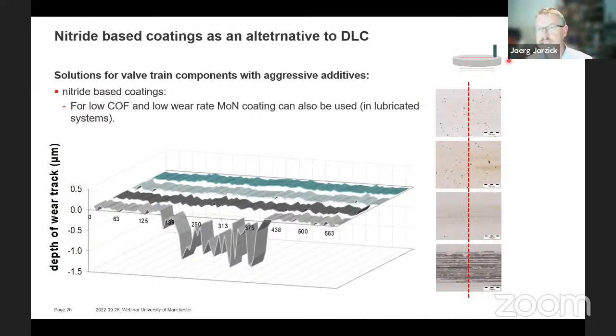So basically we coated a disc, and then we put a pin on this, and then we had this reciprocal wear test, which is a kind of standard test. And we used different types of oils, and we had a look at the wear track, and here's a picture of the wear track, and then we measured the profile across the wear track, which is displayed here. So let's start with the dark gray line. Basically, this is the standard DLC coating with a standard lubricant. And after this test, you see, okay, in the area where the pin was moving, you see some traces, but not really wear. It's just a smoothing of the coating. And if you measure across this profile, you do not see anything very interesting.